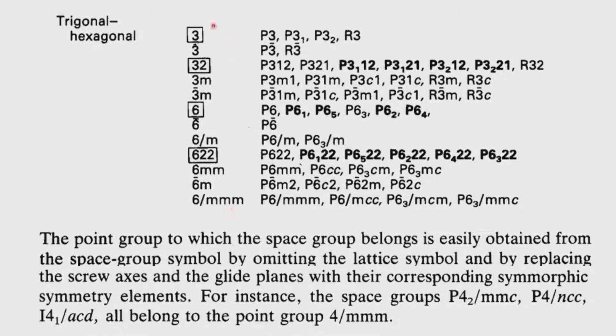So what we therefore see here is the tetragonal, the cubic, and then of course trigonal and hexagonal are given here. In the case of trigonal and hexagonal, again we should have only the primitive lattice in both these cases, because you have the angle 120 degrees, gamma is 120 degrees. So we will not have any body centered and so on. At the same time we also have this rhombohedral symmetry.